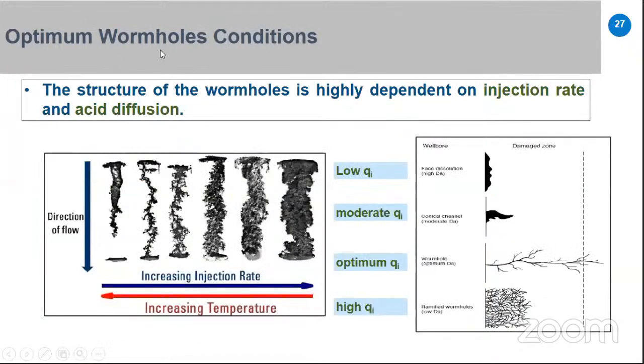The optimum condition to make this wormhole usually depends on two things. The first one is the injection rate and acid diffusion. If you inject at a low injection rate, you will only make what is called face dissolution. If you increase the injection rate a little bit, you can have what is called a conical channel. If you increase the injection rate to the optimum injection rate, you will have this branched wormhole. And if you increase it more than the optimum, you can end up with what is called the ramified wormhole.